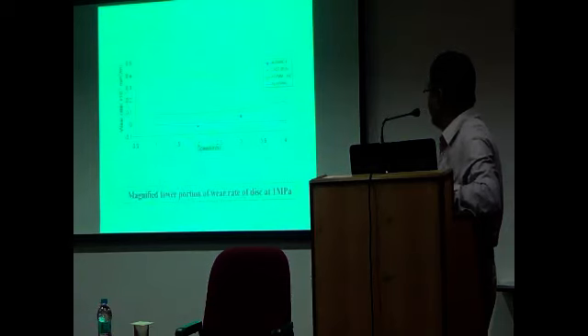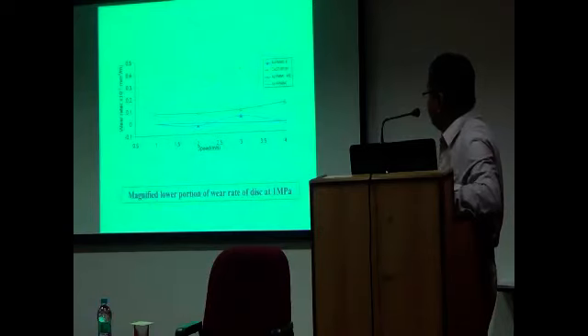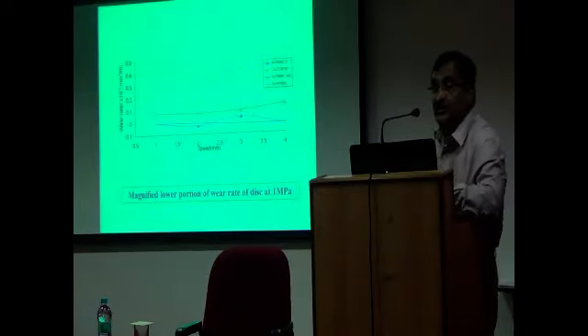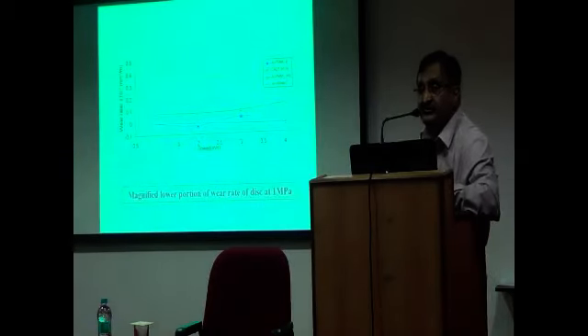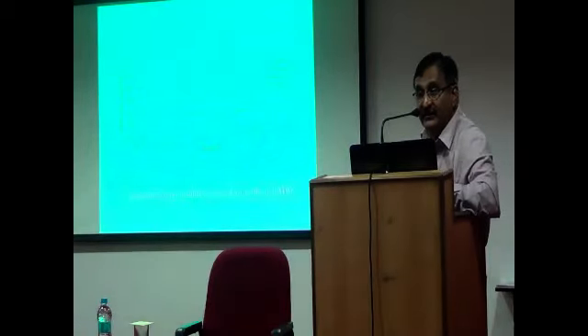The next one I will show you is where you can see the cast iron wear rate, much higher compared to the composite. So the composite that we produced by incorporating silicon carbide in aluminum has a better wear resistance than cast iron at one third the density, which made this material acceptable for various mid-sized cars and for regular passenger cars, which I will show you through a movie, which we did for the Volvo Corporation and Norsk Hydro Aluminium.